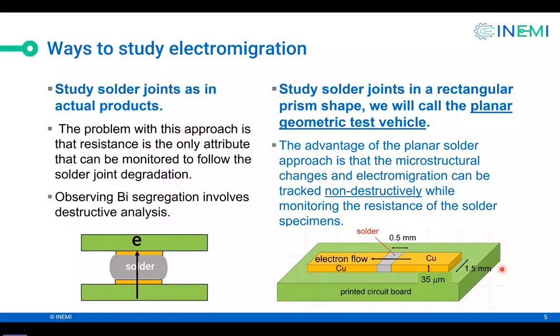So in this case, we have a very thin solder joint, as shown here in gray. The thickness is 35 micron. The length can be 0.2, 0.5, whatever millimeters you want, and the width is typically 1.5 millimeters. The current flows in this case from right to left.